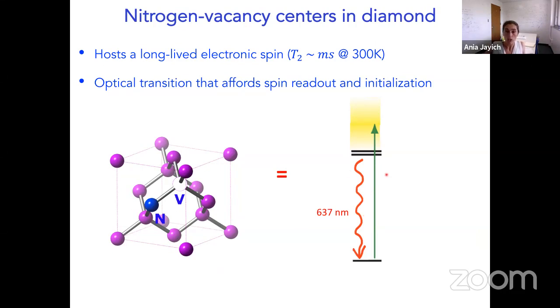So what I'll just show here, to make the analogy of the NV center to an atomic-like system, on the right is a very simplified energy level diagram of the NV center, where here is the ground electronic state, and here's the excited electronic state. In fact, the spin, that's what's missing here, but this ground electronic state actually has 3 spin levels within it, and any 2 of those can be used to form your canonical 2-level spin system. And that's the one that has a very long coherence time.